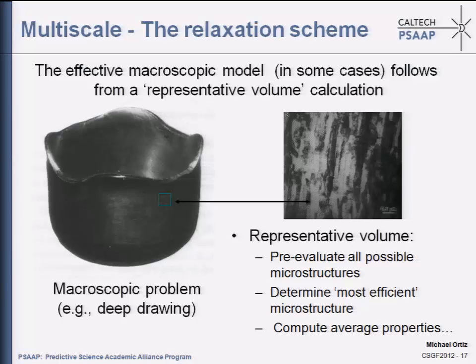Typically in metals, you have microstructures of this type. This is an actual SEM picture of a deformed metal. You see that deformations at the micromechanical level are very non-uniform. So metals form microstructure. And so the objective is somehow to pre-evaluate all these possible microstructures, somehow also determine the most efficient ones, and based on those optimal microstructures, as they're called, pre-compute the average behavior of the representative volume.